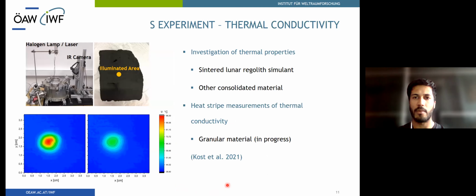In another experiment in Braunschweig, thermal properties such as conductivity and heat capacity were measured for different consolidated materials. Therefore, the cooling characteristic of a heat spot created by a laser was measured with an infrared camera and used as an input in 3D thermal models. Currently, the thermal conductivity of granular media is also being analyzed with heat stripe measurements.